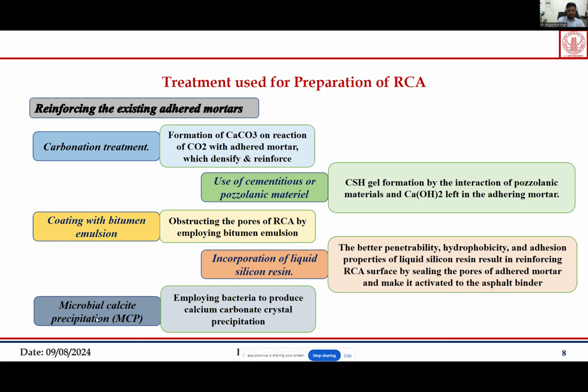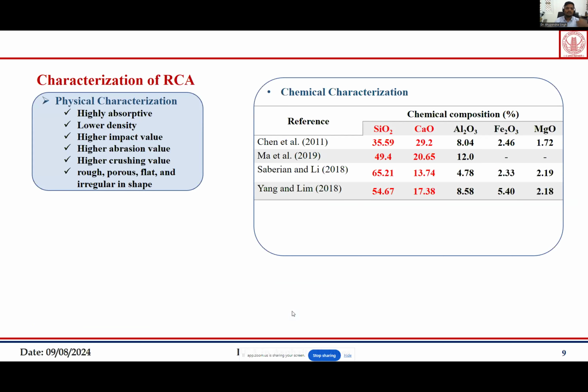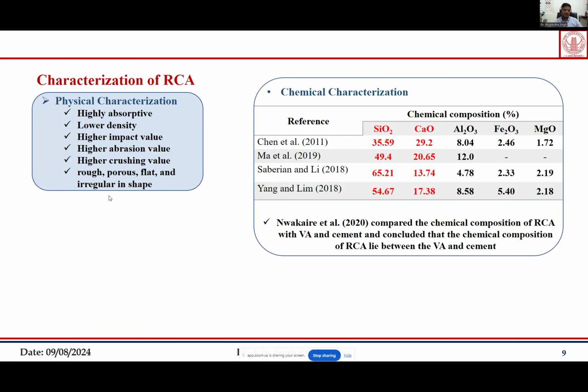People have also used incorporation of liquid silicon resin, and nowadays MICP bacteria are also used. We apply the bacteria on the aggregate surface, and these bacteria produce calcium carbonate crystals, and these calcium carbonate crystals improve the bond between adhered mortar and concrete. So these are different methods people have used. If we see the characterization of RCA, then physically we see they are highly absorptive in nature. They have lower density, high impact value, higher abrasion values, higher crushing values, and they are rough, porous, flat, and irregular in shape.